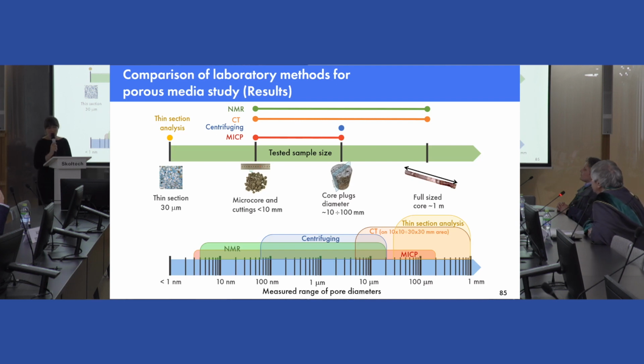Okay, yes, thank you very much. First of all, I need to say that permeability based on well logs is usually derived from the porosity log. And this is kind of looping here, and we have uncertainty here. That's the first reason why I decided to try independent logs, which also depend on similar characteristics. And yes, of course, the technique of multilinear regressions, when we have a function of not one variable but several. As the y-axis, I have the core measurements, and as the x-axis we have these variables, and that function is calibrated on the core-derived permeability.